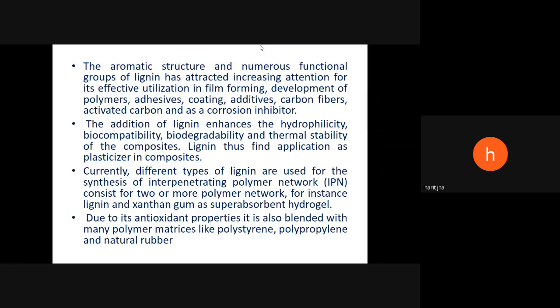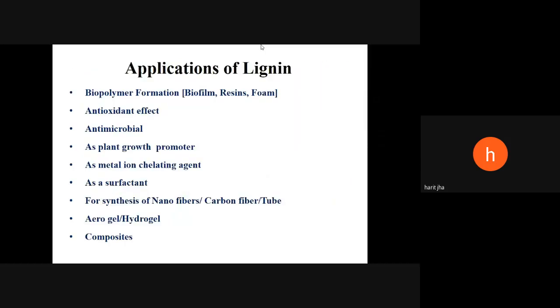Different type of lignins are used for synthesis of interpenetrating polymer network. For instance, lignin and xanthan gum has been used as super absorbent hydrogel. And due to its antioxidant properties, it is also blended with many polymer matrices like polystyrene, polypropylene, and natural rubber. So you can add lignin as an additive in these polymer matrices so that their properties improve, their aging is delayed, and strength properties are further improved. So there are many applications of lignin,